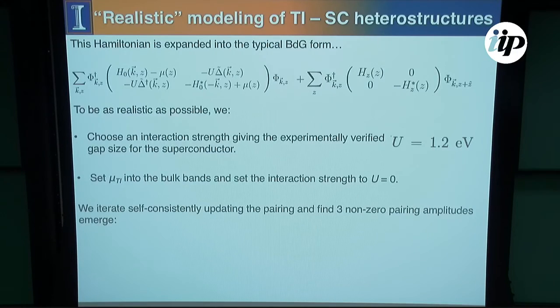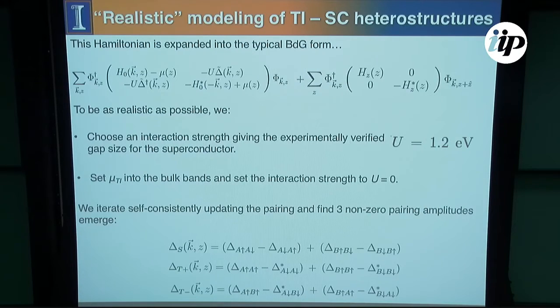So then once we've created this entire recipe, we iterate over this self-consistently, calculating the density interaction, the densities, until we get discrepancies on the order of about a microelectron volt or so. And then after that, we tried all the different combinations, because the student that I had doing this didn't look at the symmetries. So that meant there was a large panel of data that I had to look at, rather than this very small, meaningful panel of data.